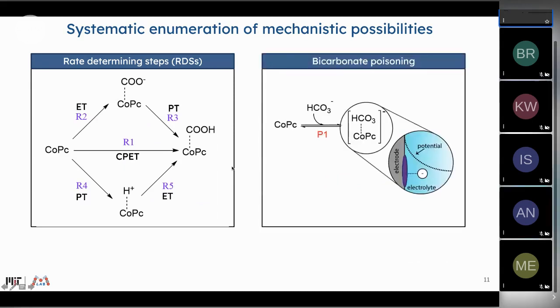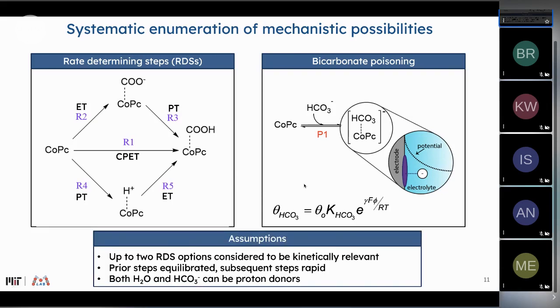We can also implement bicarbonate poisoning, where mechanistically, as we increase the bicarbonate concentration, we see apparent poisoning of the active site. We saw that in certain regimes earlier. We've implemented that using a simple electrosorption valency: there's an equilibrium constant for bicarbonate poisoning, as well as a potential dependent poisoning term. Because bicarbonate is an anion, it is attracted to the electrode at smaller overpotentials, but as we increase the reductive overpotential, bicarbonate is pushed away from the electrode surface. So there is an electrostatic mechanism that could govern whether or not bicarbonate is able to poison the catalyst.